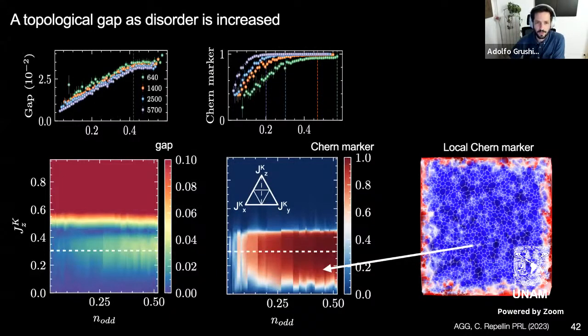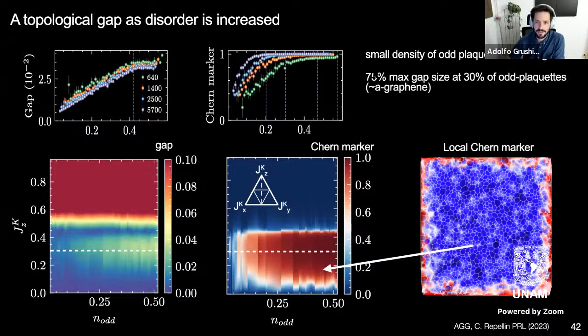You can look at how it grows, and basically what it looks like is that it's jumping straight from 0 to a finite value as you increase system size. And so the takeaway message here is that a small density of odd plaquettes is actually enough. If you take the 70%, 75% of the gap, it's around 30%, and this 30% is in fact the density of odd plaquettes that you see in amorphous graphene. So in realistic systems, you will be somewhere here, which is already quite enough to have a sizable gap, which is kind of nice.